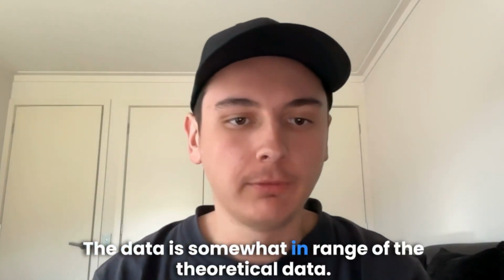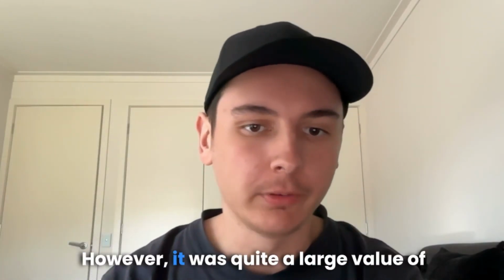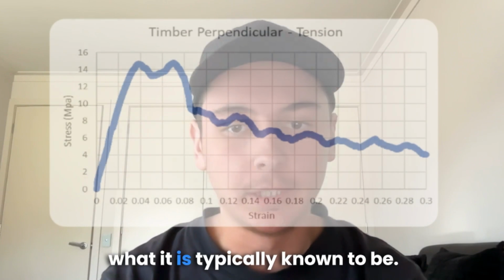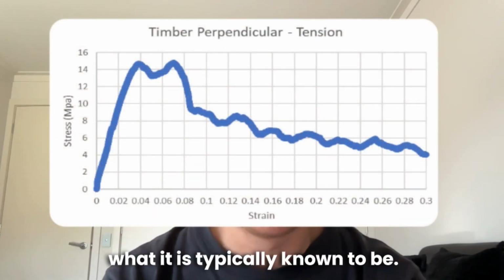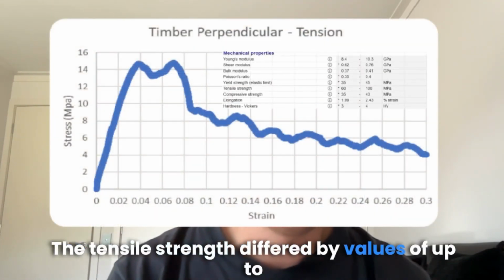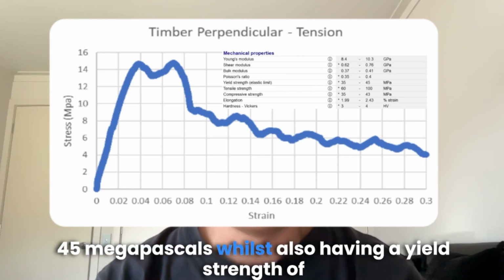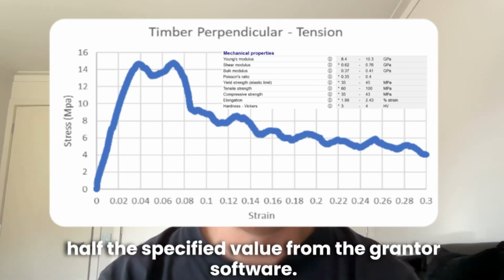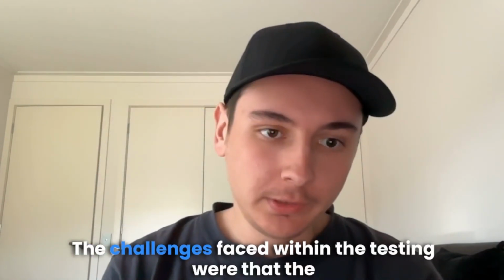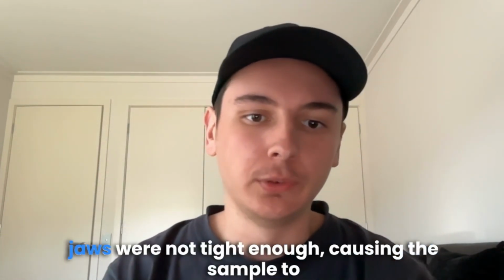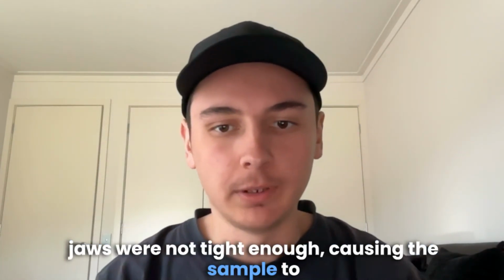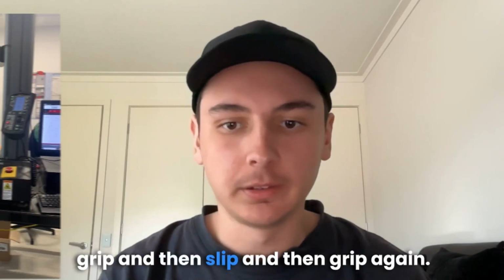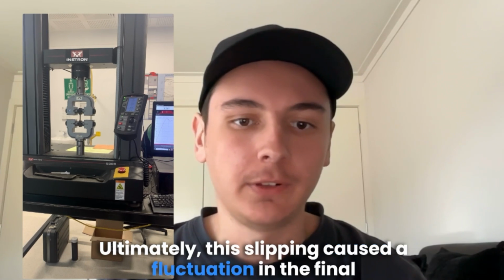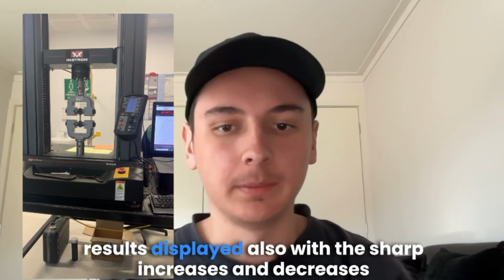The data is somewhat in range of the theoretical data, however it was quite a large value off of what it is typically known to be. The tensile strength differed by values of up to 45 MPa, whilst also having a yield strength of half the specified value from the Granta software. The challenges faced within the testing were that the jaws were not tight enough, causing the sample to grip and then slip and then grip again. Ultimately, this slipping caused a fluctuation in the final results displayed.